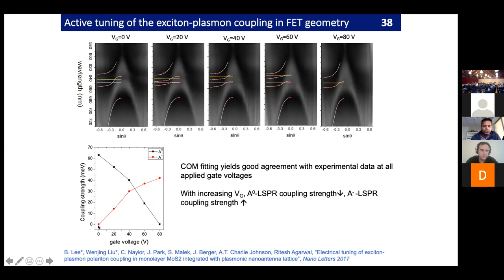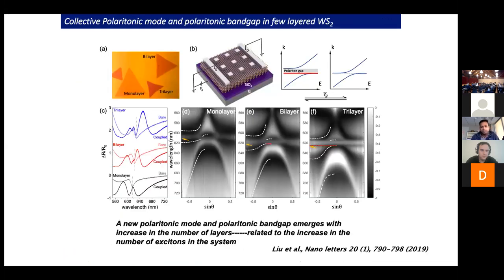And for the trion, it goes from no observed coupling to something in the intermediate coupling regime. So the idea is that given this very interesting material, if you do this with any material which is slightly thick, even something which is 5 or 10 nanometers thick, one would have to do something more dramatic because the gate effect is mostly at the interface of the oxide where the gate voltage is applied. But because it's a monolayer of material, there's no place for these excitations to hide. So they're forced to interact. And because of weak screening, the influence is very strong.